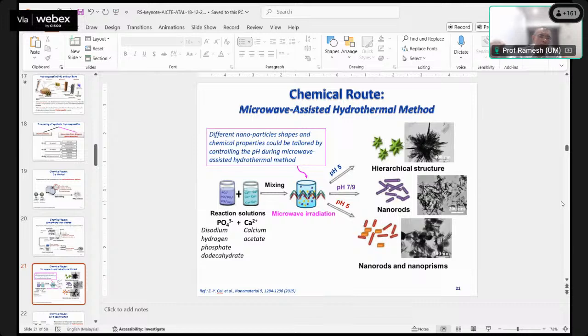I have always stuck with the chemical precipitation method because, based on the readings that I've done, it is much more superior in terms of yield, reproducibility, and quality, rather than all other techniques. All other techniques are good for publishing papers. You do a little bit of mixing here, change a bit of parameters, you can write good ISI papers. You get nice structure and then you can publish. But for application, I think it's a bit difficult to scale up and to control the required morphology.